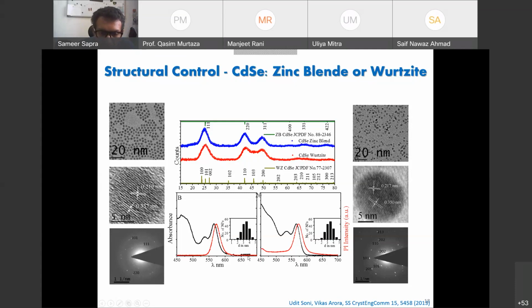The other way of characterizing these materials is doing UV absorption spectroscopy, and you'll observe that you start to see all these excitonic features, the first, the second, the third, the fourth. Same in both the cases. And you also observe fluorescence. This particular fluorescence is in the yellow. By the way, the band gap of CdSe is about 720 nanometers. So this is much higher than the band gap, lower wavelength. These are known as quantum size effects.